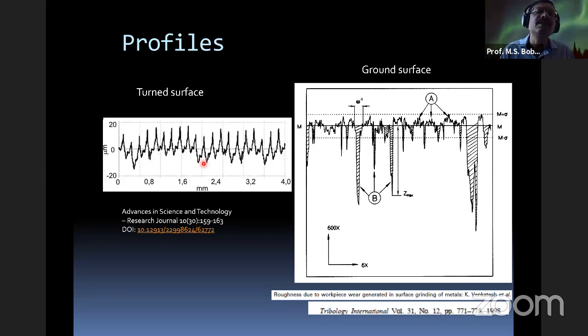You can see, this forms the lay. The periodic peaks form the lay, and there is roughness in between that. On the right hand side, you see this is a ground surface. You see here, this is 4 mm in the horizontal axis, whereas the vertical axis is only 40 micron. So it is 1:100, the magnification factor between the x-axis and y-axis. If you do 1:1 magnification, the peaks will be very, very tiny. It won't be like this, it is stretched out. So it is not really so much rough.